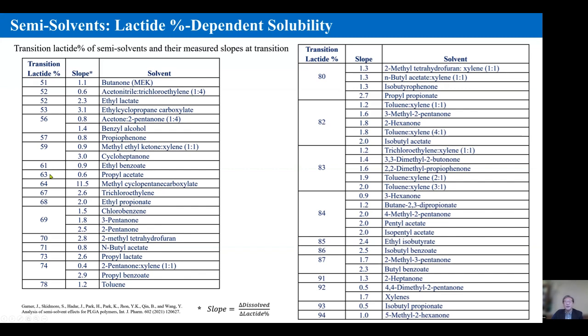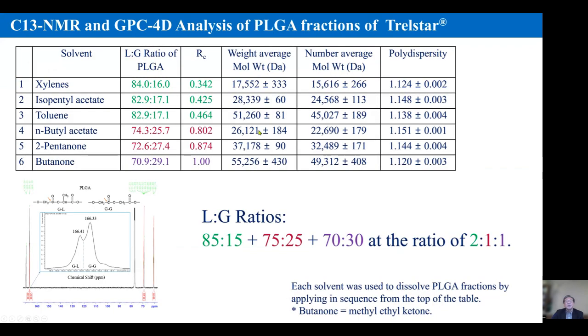Okay, that's the beauty of this study supported by FDA. We can separate PLGA regardless of the LG ratio. As long as they are different, we can separate them. So having all this separation and characterization that we went through, we noticed that there are at least three different groups. The first group, LG ratio is about 83-17, and then the other is about 73, the other is 70.